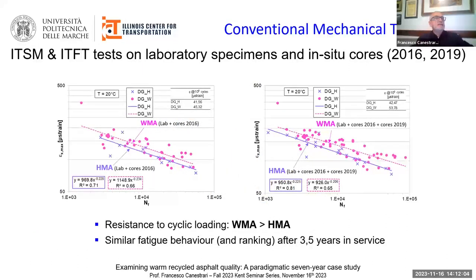In this slide, there are the results in terms of resistance to cyclic loading. In general, we can see that warm mixtures showed higher resistance to cyclic loading than hot mixtures. More in detail, on the left, there's the comparison between the fatigue resistance of hot and warm mixtures based on laboratory specimens and in situ cores taken in 2016. On the right, we have the same comparison obtained by adding the results of the in situ cores in 2019, where we can see that after more than 3 years in service, the fatigue behavior and the ranking of both mixtures remains basically the same.